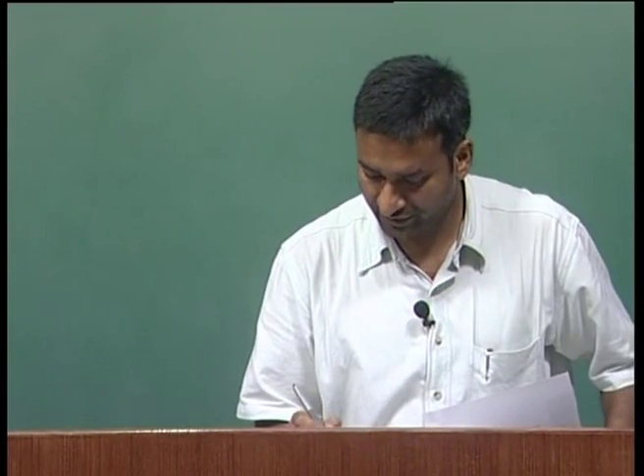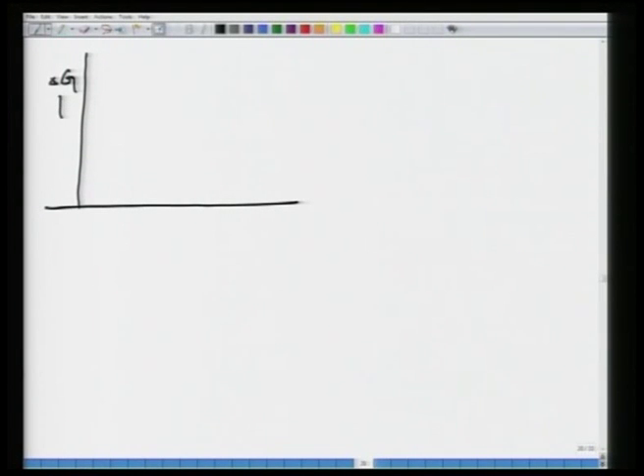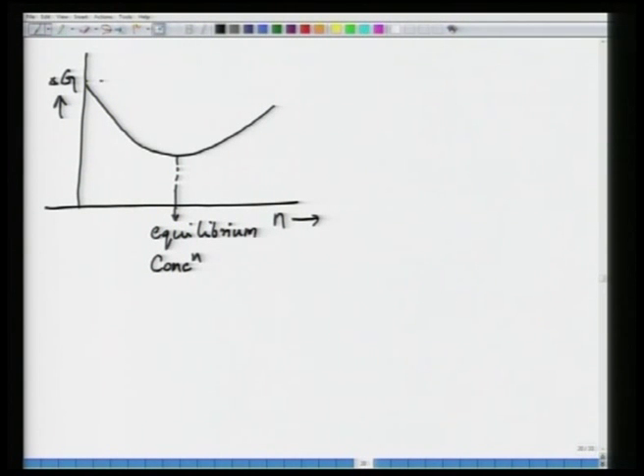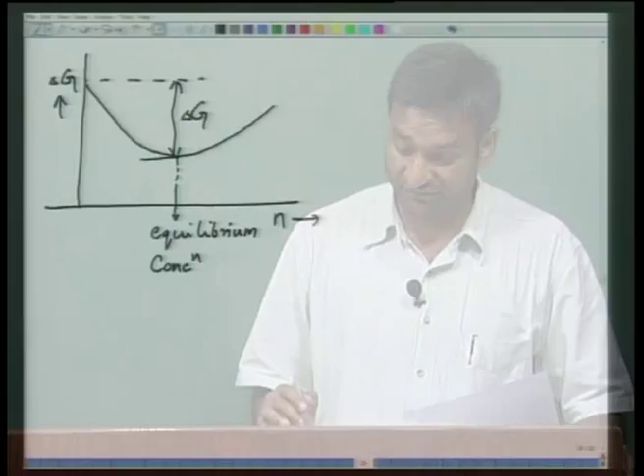So, if you plot delta G versus n, let us say the n defects, it is going to be something like this. You can simulate this graph as well, and this minima will correspond to the equilibrium concentration, because here the free energy of the crystal after formation of these many defects will be minimum. So, what we now need to do is differentiate that particular equation which we wrote in the previous slide with respect to n and find out what is the equilibrium concentration of defects. So let us do that.